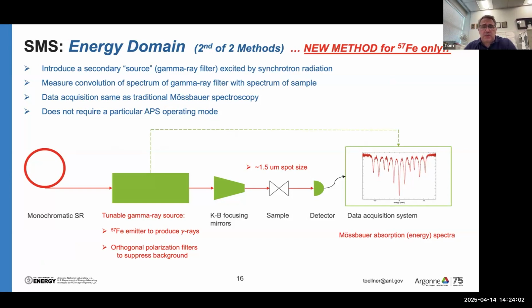The net result is we end up with a setup that's rather similar to a traditional Mössbauer spectroscopy setup, where one scans the energy by moving the gamma ray source on a velocity drive and then correlating that with the arrival time of the photon in order to bin all the events as a function of velocity, and velocity corresponds directly to energy. This can be done in any timing mode, and the result is going to be a convolution of the gamma ray source with the sample. That is what the measurement involves.